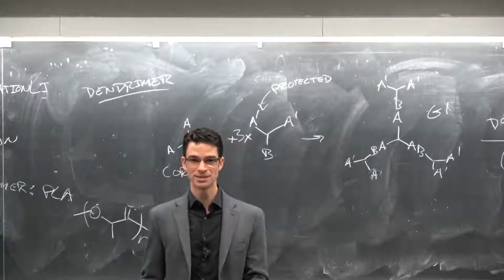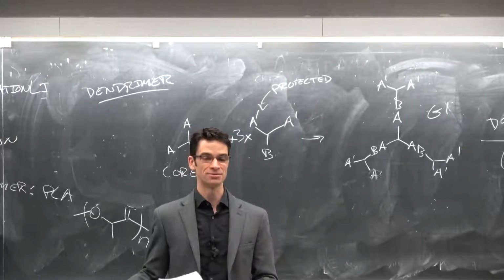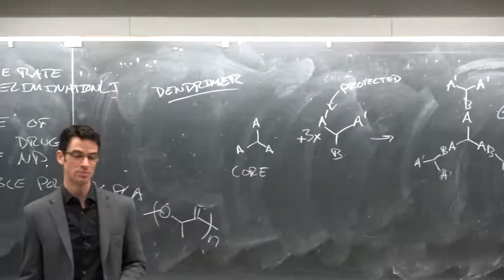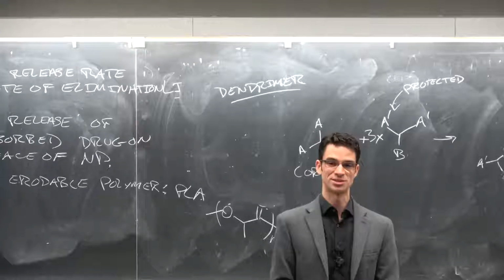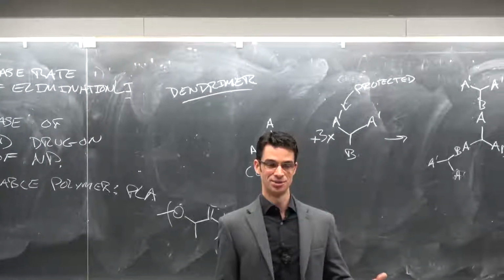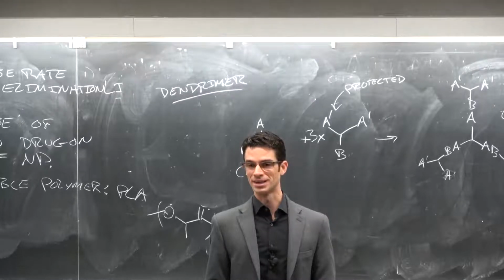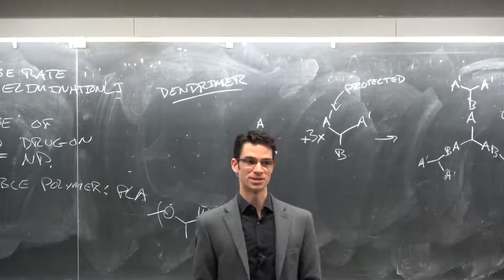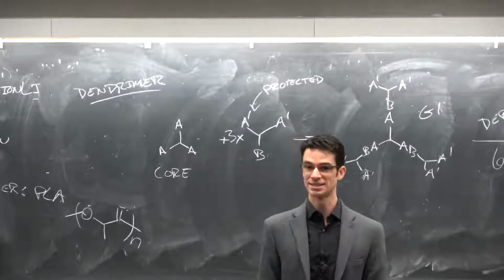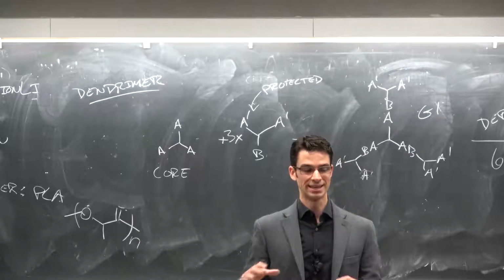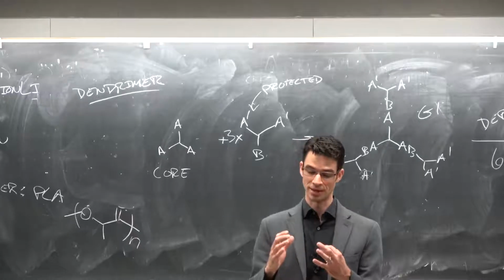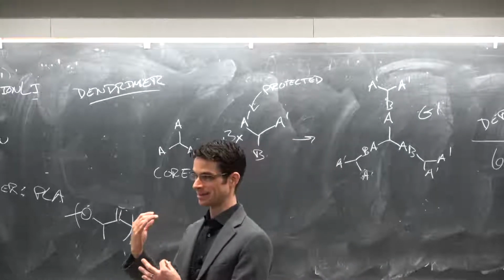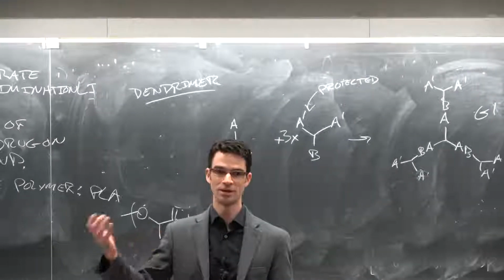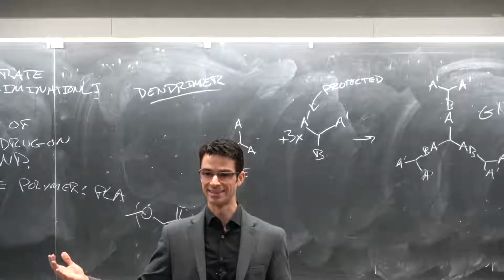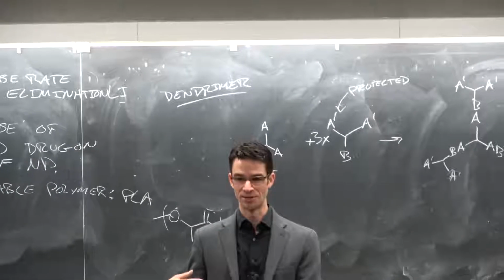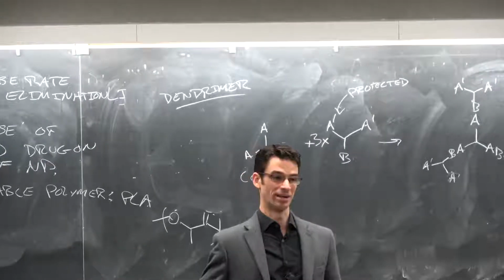So you pegylate the surface, and PEG has a characteristic that it's not targeted for removal by the immune system as readily, although a good fraction, like a quarter of patients, will actually develop antibodies against PEG to remove these structures. Another technique used by Professor Zhang at UCSD is to use red blood cells. You take the red blood cells and you bust them up, and then the cell surface proteins and the lipid layer, the membrane, will actually reform around polymer-based nanoparticles, and then your body thinks that there are little red blood cells floating around, and then they can go around with impunity wherever they want in the biological system.